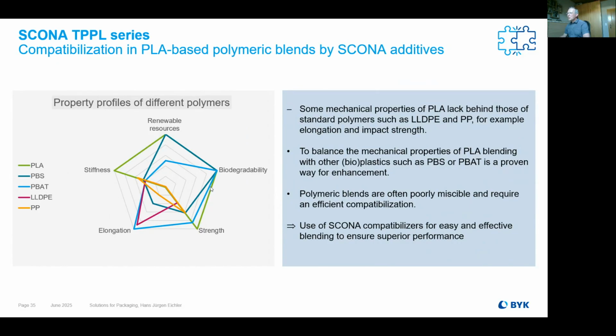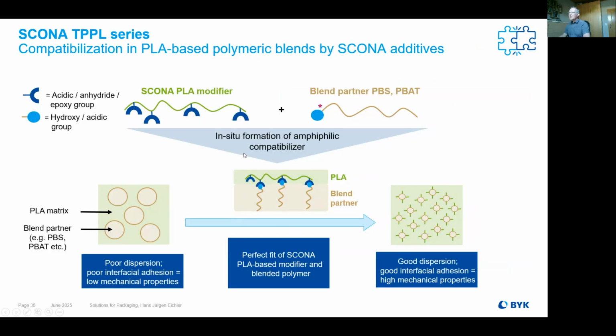And here again, our Skona compatibilizer can help to incorporate these different bio-based polymers. Same mechanism like I showed for the polyamide PE modification, but now we have another partners to play around. So we have, of course, again, a maleic anhydride Skona material, and we have a blend partner, which might be the PBS or PBAT. And what is going on now? The Skona PLA modifier is reacting with the blend partner and made again a good dispersion and improve mechanical properties and the adhesion from the materials.